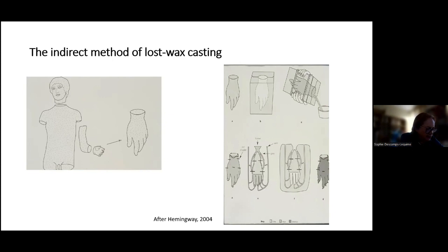The thickness of the metal walls, equivalent to that of the wax, was now reduced and regular. It is this control that limited casting accidents. The model and the master molds were preserved. After this first step, the wax working model was cut again, and the next steps were identical to those described for the direct process: metallic chaplets, network of gates, funnel, vents, clay investment, and so on.